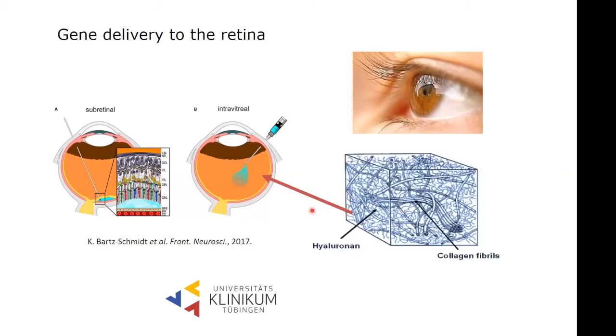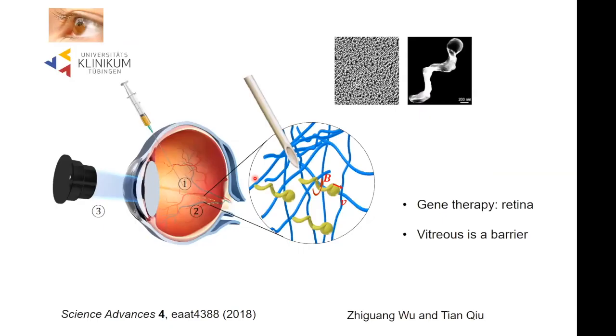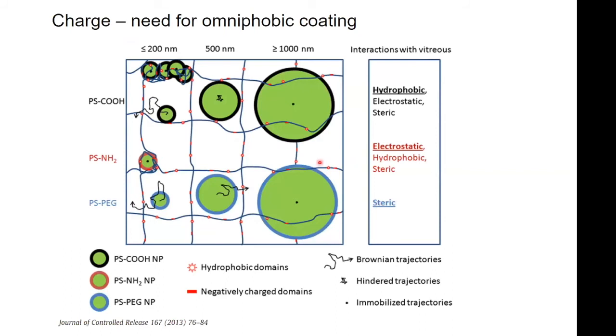And same problem, the vitreous is a hydrogel-like structure with hyaluronic acid and collagen fibrils, so it will have a network. We can build small structures, and we can try to inject and then move these structures towards the retina. The size should be correct, as we've established. Do we also encounter some kind of challenge like we did in the mucus? And the answer is, again, yes, nothing simple.